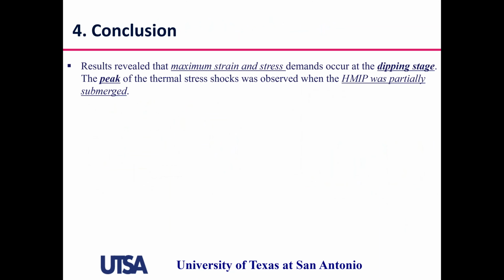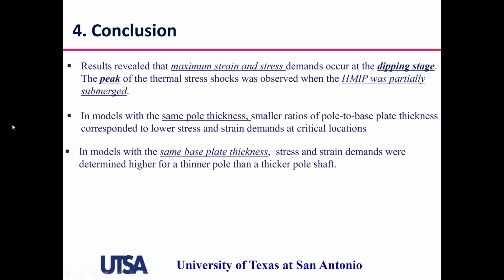So, some conclusions. We saw that the results revealed maximum strain and stress demand at the dipping stage. That's where we saw the thermal shock. It was the highest when the HMIP was partially submerged. Then through the parametric study, we saw that poles with the same pole thickness and smaller ratios of pole to base plate thickness correspond to lower stress and strain demands at critical locations.